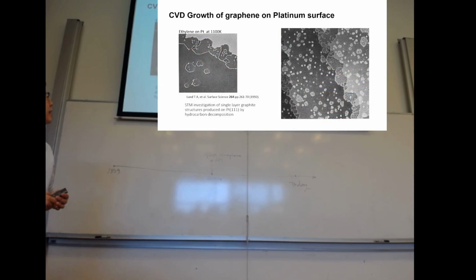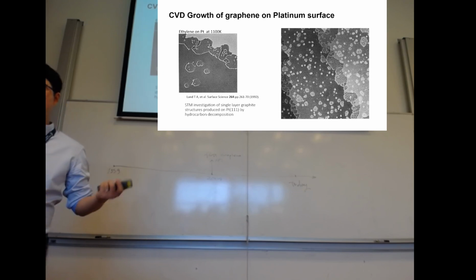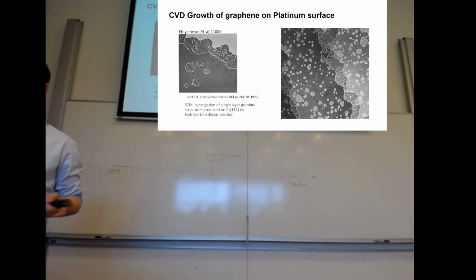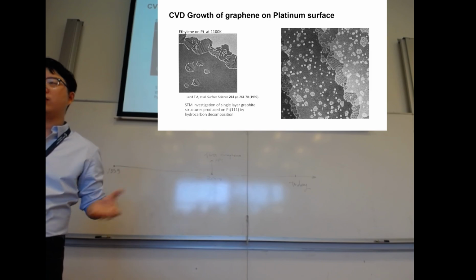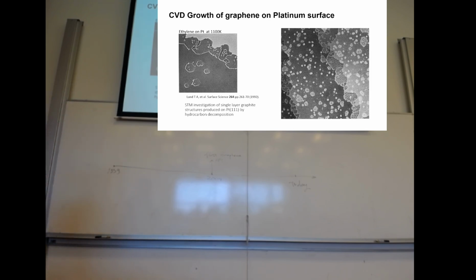And then you can see that actually graphene is not new at all. If we really dig into this literature, the growth of this material started in even 1992. There is a surface science paper where they did STM studies of single layer graphite. They don't even call it graphene because nobody really paid attention to that. But this is graphene. You see the honeycomb lattice is well reproduced on a platinum 111 surface, and that's a very good example of how people obtained graphene using experimental techniques.